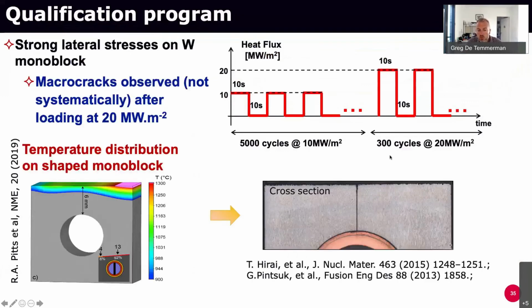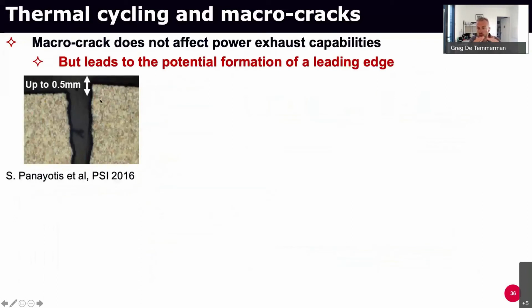And what we know is that when you have that, at some point you could have cases like this picture of those monoblocks I showed you, with a very big crack forming inside the block, which the engineers tend to call self-castellation, because the material cracks so that it accommodates the stress better. And you see in some cases, this is about 8 millimeters of tungsten thickness, the crack has gone all the way through, close to the cooling tube. This could be an issue for the cooling process, but also because you then have two sides of the crack, and you can have a height difference, a misalignment between one side and the other, which can be up to 0.5 millimeter.